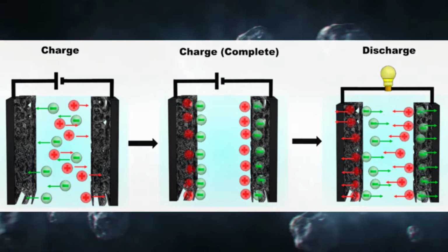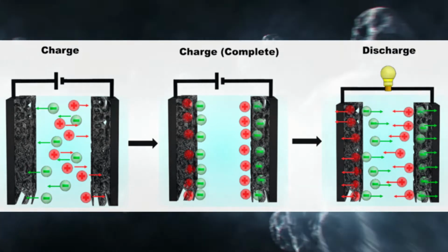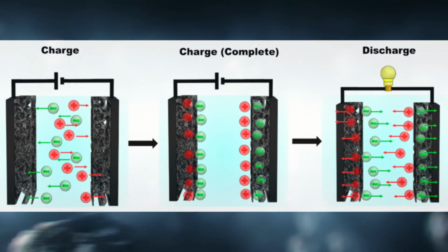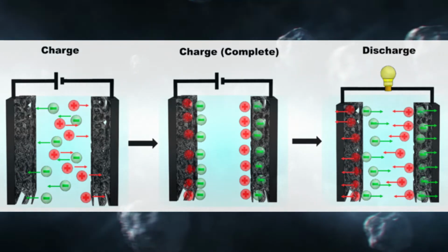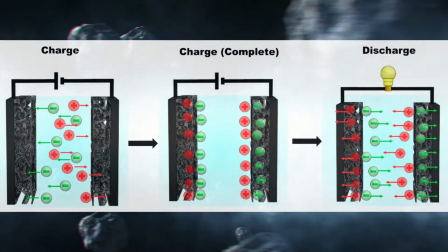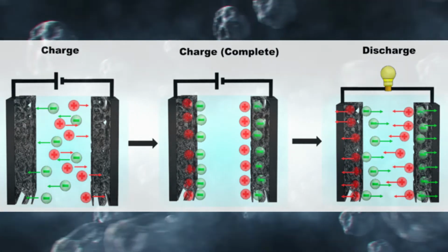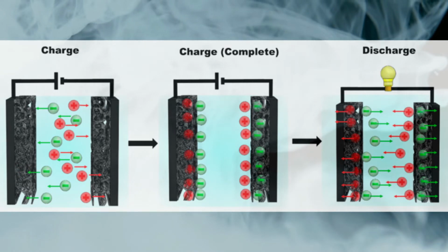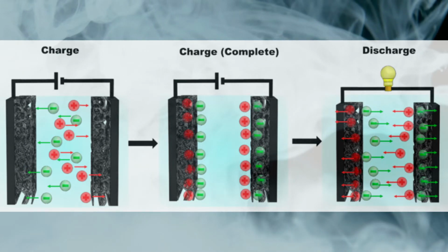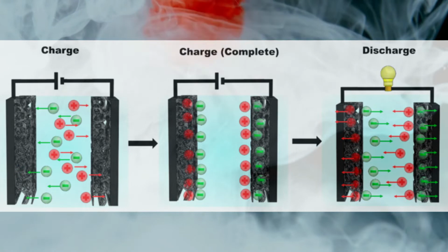In general, these carbon-based materials alone are electrochemically inert, and the energy storage only takes place due to the accumulation of the charges, ions on the electrode surface. The carbon or composite material-coated electrodes can act as active materials and/or collectors. In principle, carbon-based supercapacitors contain an electrical double layer formed at each carbon interface, where the carbon material is in contact with the electrolyte. When the supercapacitor is charging, the negative ions and vacancies on the cathode, and the positive ions and the electrons on the anode are arranged across the interface. This arrangement of ions and electrons, vacancies, during the charged state is known as an electrical double layer.